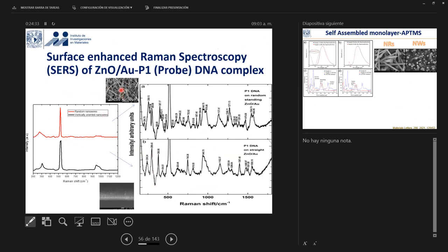In this case, we have random nanowires and vertical nanowires, and you can see the Raman spectra of these nanowires. They were quite similar before functionalization. The red one corresponds to random nanowires, and the black one corresponds to vertical nanowires. Before interaction, they were the same. When we did the interaction, you can see the number of peaks changed, and you can easily see the differences before and after. Between these two structures, random and vertical nanowires, the number of peaks is different, and the interaction level is different. The main conclusion in this work was that the random nanowires were much better for the optical detection. They were more sensitive compared to vertical nanowires.